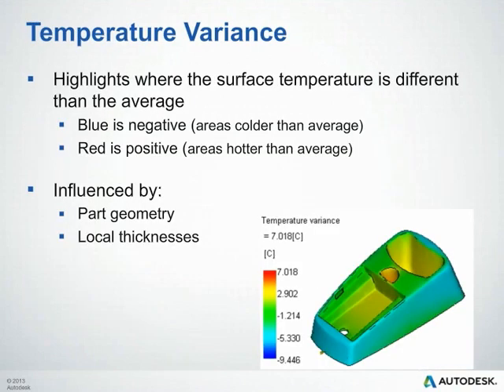The Temperature Variance plot highlights where the surface temperature is different from the average temperature — blue (negative) areas are colder than average, red (positive) areas are hotter than average. This plot is mainly influenced by part geometry and localized thicknesses. Keep an eye on the range on your scale: the smaller the absolute value, the better. Under 5 degrees Celsius (9°F) is optimum for semi-crystalline or crystalline materials. For amorphous materials, you can sometimes keep this range under 10 degrees Celsius (18°F).